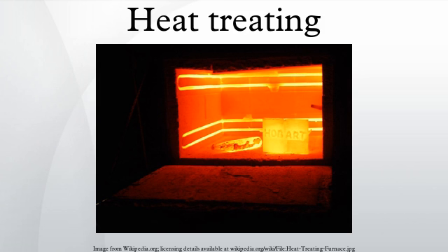Case hardening. Case hardening is specified by hardness and case depth. The case depth can be specified in two ways: total case depth or effective case depth. The total case depth is the true depth of the case. The effective case depth is the depth of the case that is a hardness equivalent of HRC 50. This is checked on a micro-hardness tester. This value can be roughly approximated as 65% of the total case depth. However, the chemical composition and hardenability can affect this approximation. If neither type of case depth is specified, the total case depth is assumed.